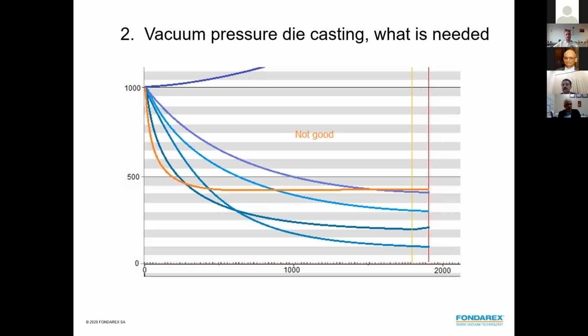Afterwards, we can set limits in the vacuum unit, so that if we are out of tolerance, that means higher than 200 or maybe lower than 100, we are not in the field of how the overall parameters are set in the pressure die casting application. So this is a little bit how to start. We do not know on paper or on a computer exactly how much vacuum we have to have. We have to work out how much vacuum the die gives and what kind of parameters we can set together with the die cast machine, with the mold, with the application we have.